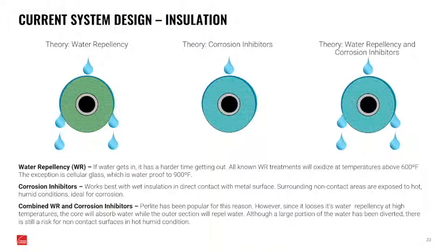think about. And then finally, we have kind of the belt and suspenders approach, where you would have water repellency coupled with corrosion inhibitors, so that you're repelling water, and any potential water that does get in, you have a corrosion inhibitor to deal with it. So you have kind of the best of both worlds there. Unfortunately, it doesn't always work out that way. A lot of water repellency treatments will burn off at 600 degrees Fahrenheit or so. So any material that sees that, usually close to the pipe, is going to be burned off and actually can become more water absorbent, and it will actually absorb the water.